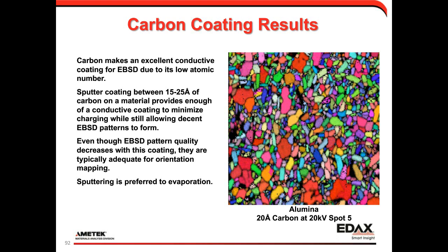I prefer sputtering to evaporation. That's based just on control. It's easier to repeat, and it's easier to repeat from one sample to the other. Again, that's very equipment dependent. And then no matter what you do to your sample, you want to make sure your coated samples still have a path to ground. And so if that's conductive tape, a conductive mount, conductive paint, it's still necessary to make sure that your charge can go from your sample to ground and not disrupt your patterns.